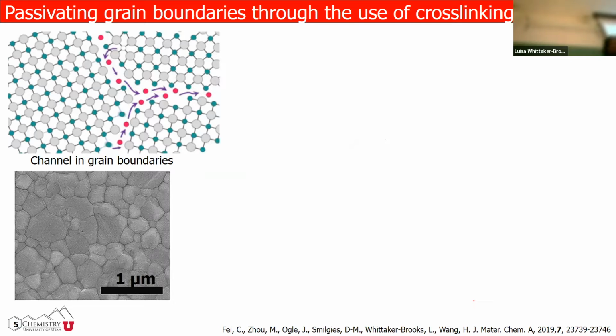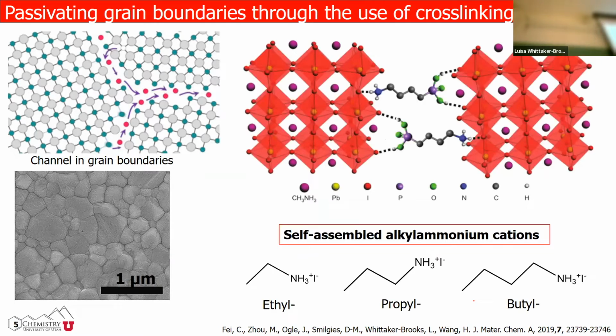So the way that we thought about that is just using a chemistry approach and said, well, can we actually glue these grain boundaries with these self-assembled alkyl ammonium cations? So we basically have these molecules right here. We add it to our solution, and then we spin coat our material, and then see how it affects the kinetics of the crystallization process to change the formation of crystals. And in that regard, the grain boundaries of these materials.